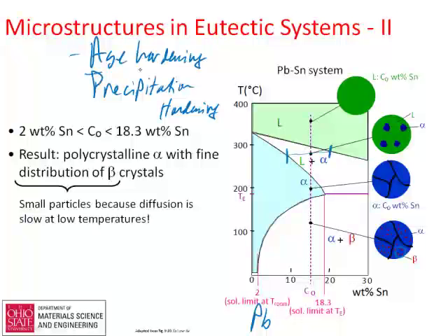If you're going to do age hardening or precipitation hardening, you quench to a low temperature, giving you a non-equilibrium, supersaturated solid solution, and then you heat back up to some modest temperature, and that lets this come closer to thermodynamic equilibrium. It allows diffusion to happen and starts giving you small particles in there. If you just cool slowly, diffusion is easy, and the beta particles form where it's easiest, usually along grain boundaries, these intercrystalline boundaries you heard about before.